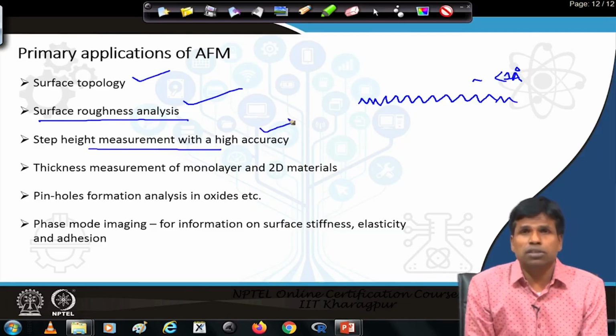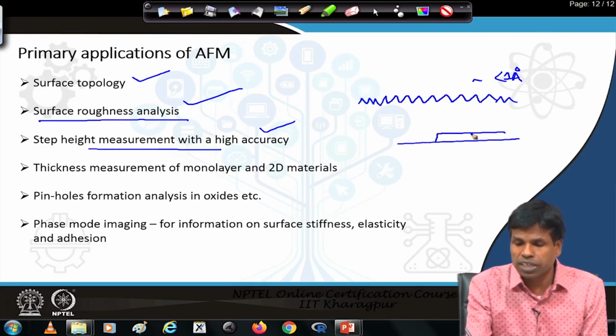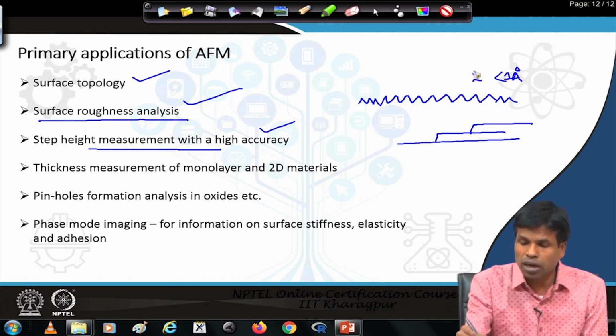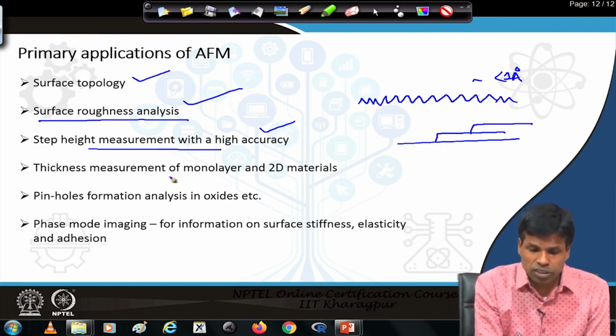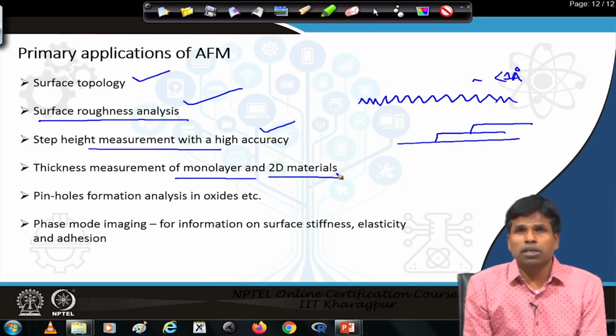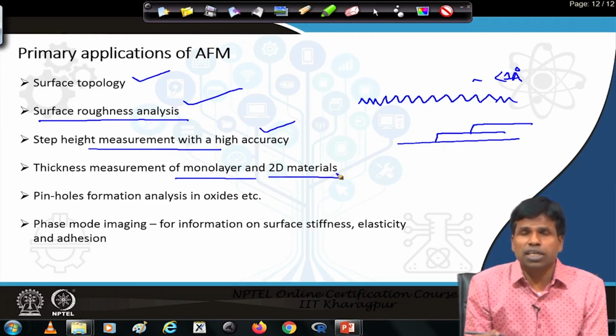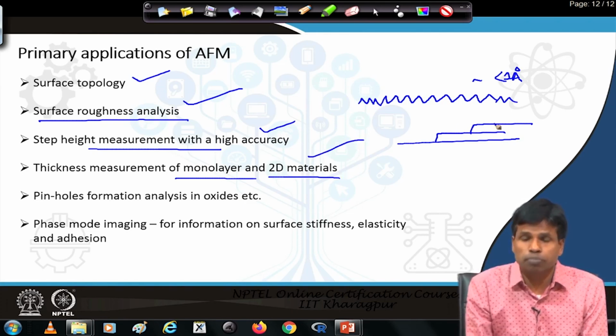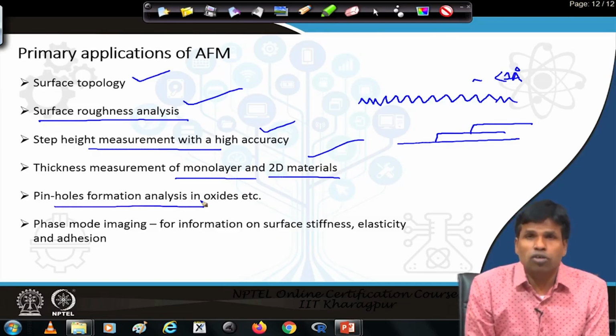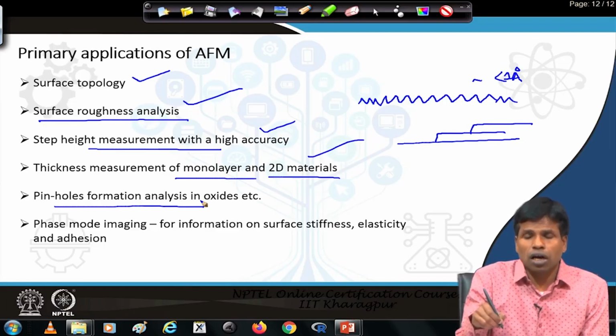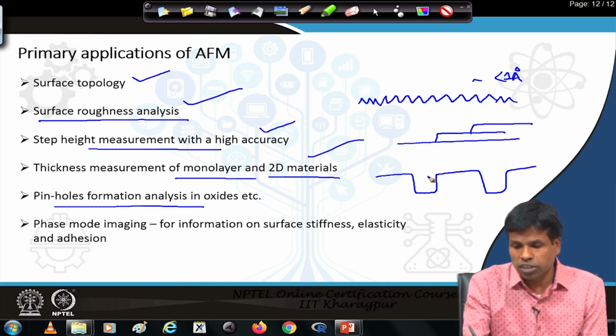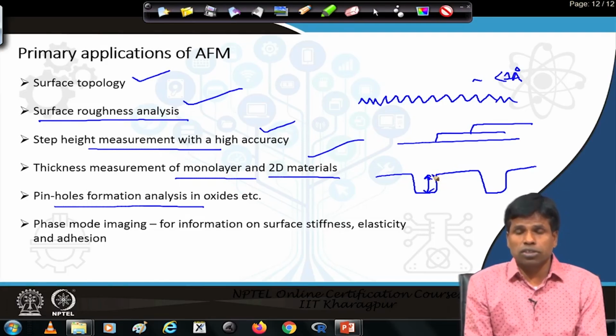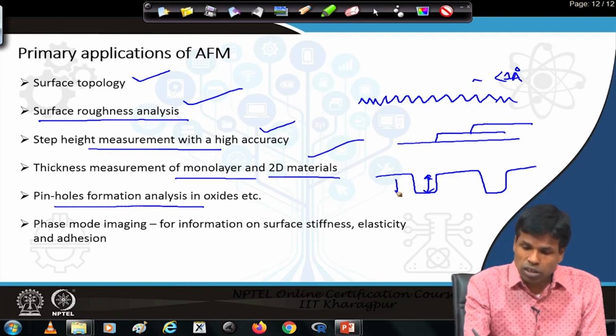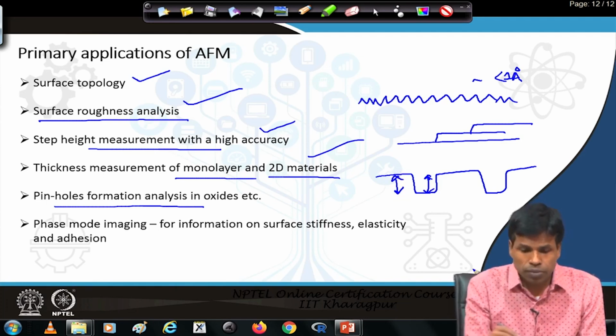Step height measurements with high accuracy. Step height means in lithography and in device making there are different steps. We can measure the height of each step in the angstrom range. Certainly, we can measure the thickness of monolayer or 2D materials like graphene, nanosheets, all these kinds of 2D materials; thickness is most commonly measured by atomic force microscope, the same way the step height is measured. Pinhole formation analysis in oxide. So, if there are pinholes in a surface, we can accurately measure the height or depth of the hole, which cannot be measured by other techniques such as scanning electron microscope or helium ion microscope. Quantitatively, we cannot measure the depth or vertical height with those, but atomic force microscope and scanning tunneling microscope can be used for this purpose.